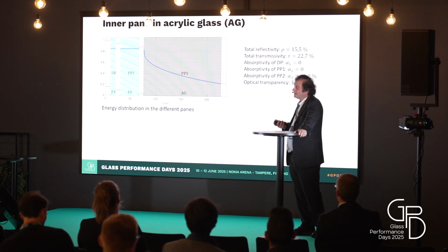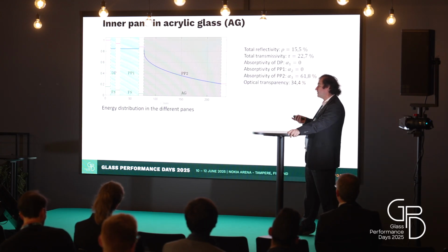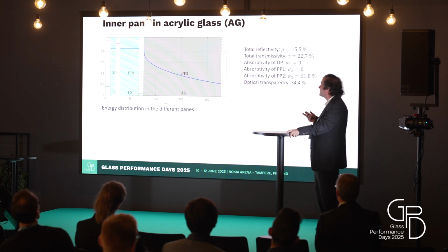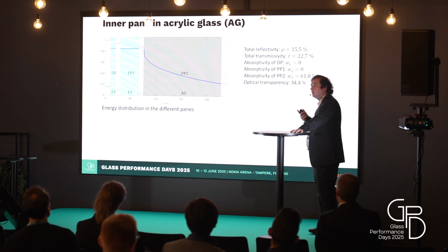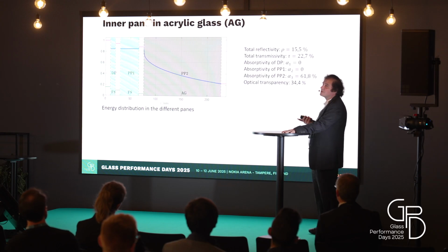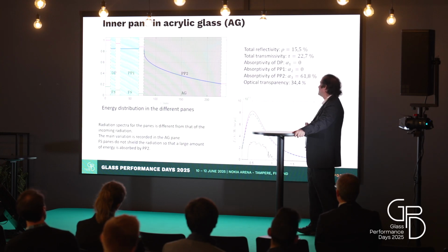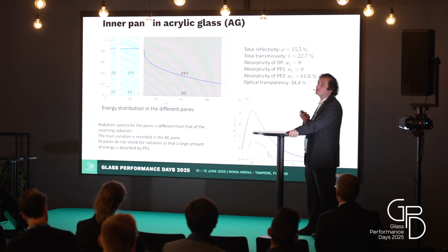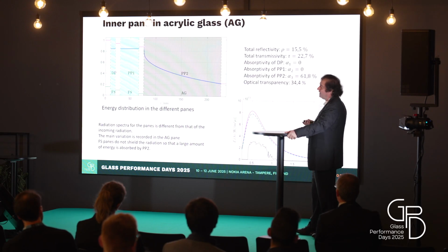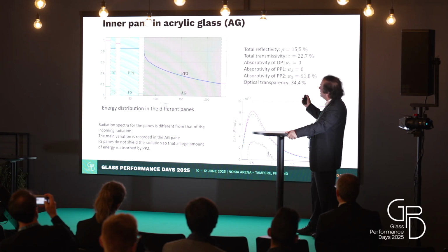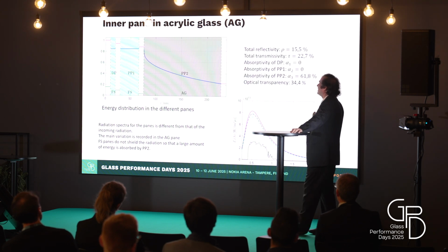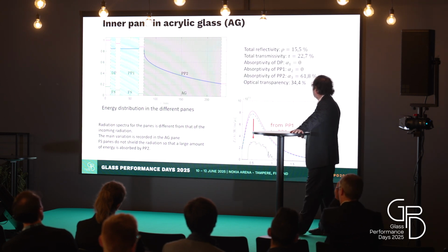Now we made an exercise. Since acrylic glass is being used, what would be the difference if you substituted one of the panes with acrylic glass? Of course, you have to consider very thick acrylic glass in order to have the same thickness as fused silica. And what you can see now is that the acrylic glass takes most of the radiation, because it is the only material that absorbs. There is also a heat exchange between the panes due to the radiation of acrylic glass on fused silica.